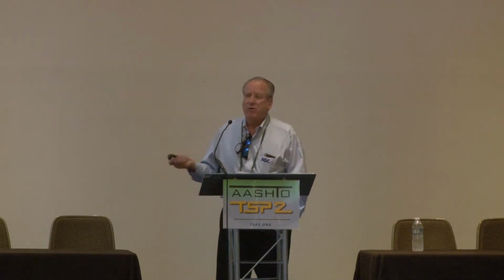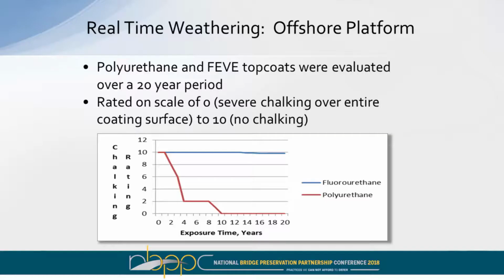What they're showing here is that the polyurethane material, basically that 1 mil or 25 microns, is gone after 13 years. The FEVE coating of that original 1 mil, about 21 microns, which is about 85% of the coating thickness, still remains after 16 years of exposure, which is pretty remarkable. You're really looking at erosion by rain and wind and things like that when you start to talk those type of numbers. This is a chalking test on the same platform.